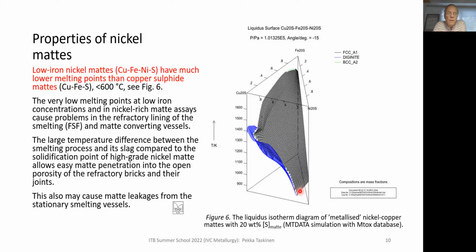This is a nuisance in industrial nickel making, because smelting takes place where the slag is molten, and depending on the MgO concentration of the slag, the smelting takes place at 1350, 1400, 1425 C.